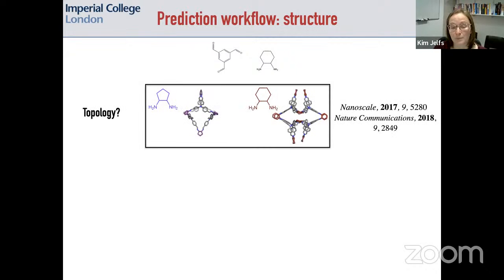And there's different levels of that. So first of all, you have what is the topology that you're forming. I've just shown you that there can be various options depending on the connectivity of the precursors. And you might think that maybe this should often be intuitively obvious, but it can be surprisingly subtle and easy to get a different topology outcome from quite small changes of the precursors. So what I'm showing here is if you have a reaction with the same tritopic linker, the one shown in grey, but you change the vertex only very slightly, then you get a totally different outcome.